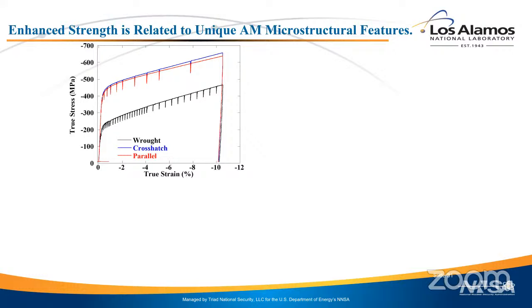So this is, in some sense, completely different. Once you've actually AM'd the material, and I said this early on, the properties of the AM material are often very different from traditionally cast and wrought material. And I'm showing that here. This is a stress strain curve of 304L stainless steel. This is powder bed additive manufacture.